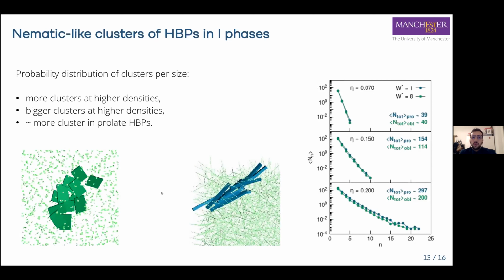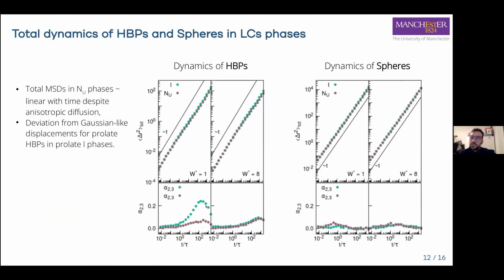And for this reason, we computed the probability distribution of clusters per size. And we observed that passing in isotropic phases from low to high packing fraction, we observed the formation of more and more clusters in number and bigger clusters in size. And prolate particles, prolate cuboids, tend to form more clusters at higher densities and bigger clusters, so clusters with more particles at higher densities. And we think that this is the reason why we observe this strong deviation from Gaussianity specifically for prolate particles rather than oblate particles.